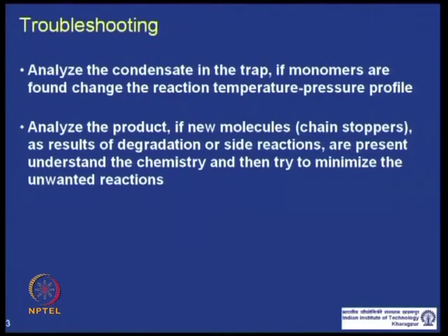What you have to do to tackle this is understand what is going on, understand the chemistry behind this side reaction, and then do your best to minimize these unwanted reactions. Sometimes the catalyst which you are using in the reaction might be one source catalyzing the side reactions as well. So, you might consider changing the catalyst or even reducing the catalyst amount, so that your side reactions come down as low as possible. One side reaction we can consider is during polyester formation.